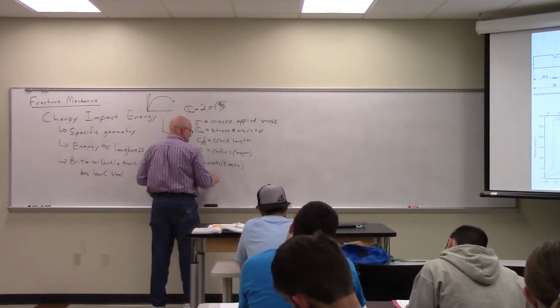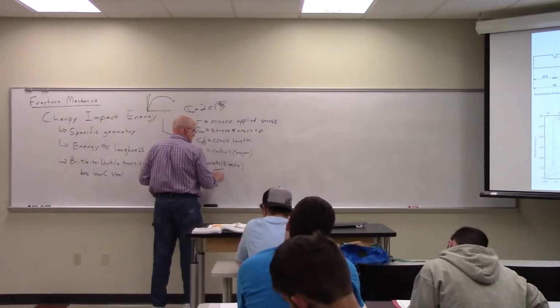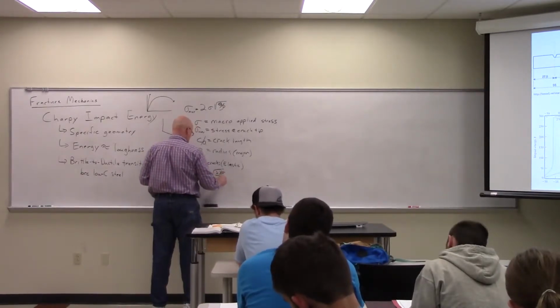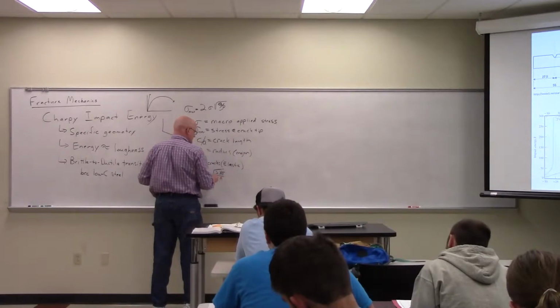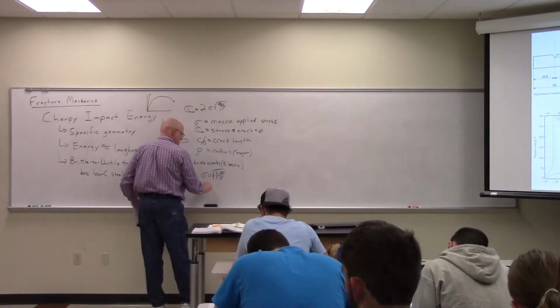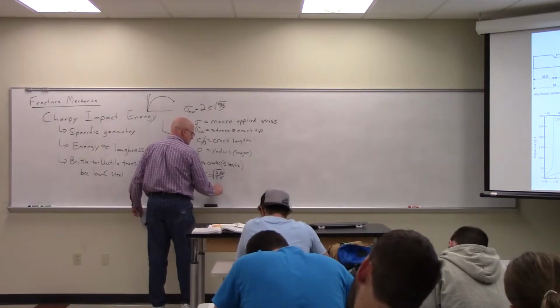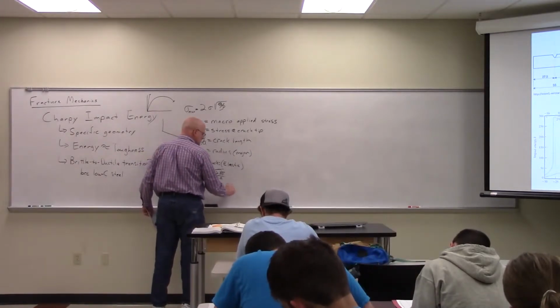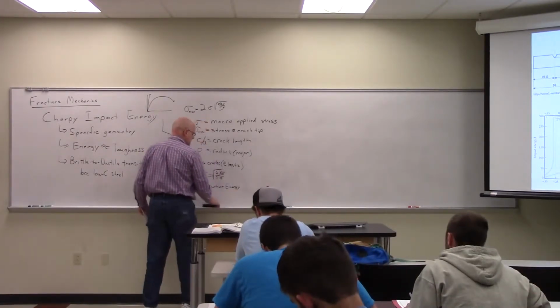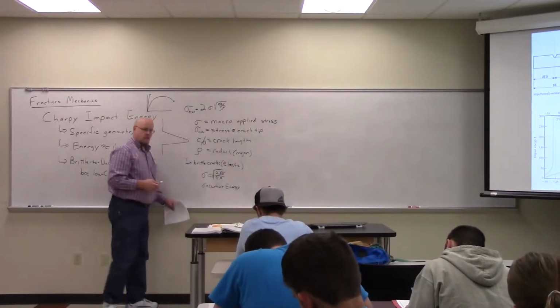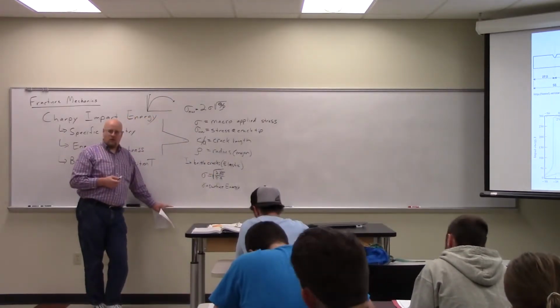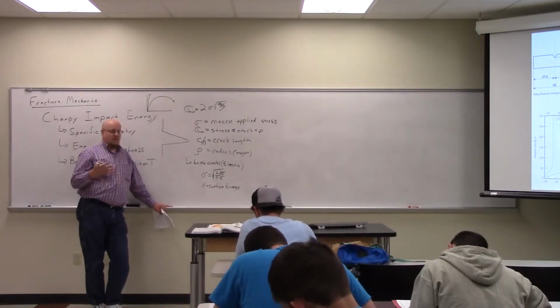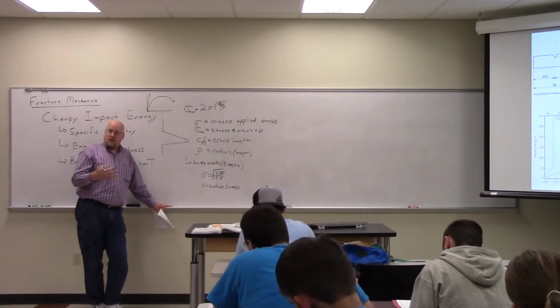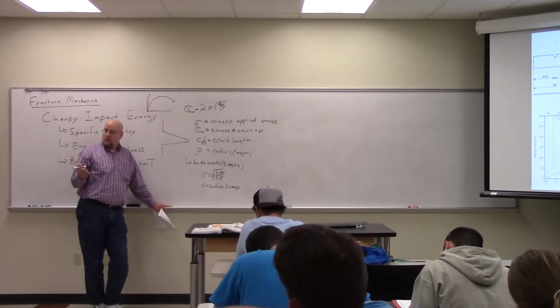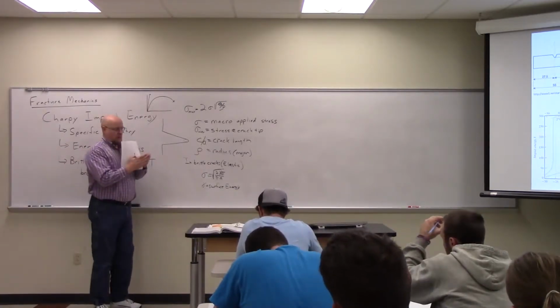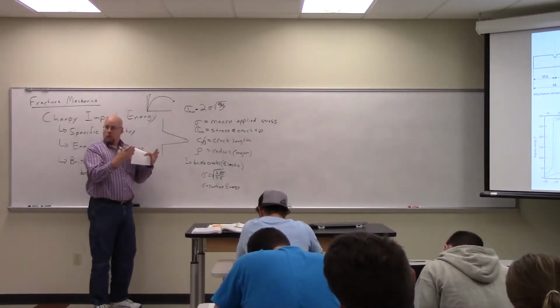So this is the square root of 2 gamma E over pi A. This is not in your book, I don't think. I couldn't find it. Where gamma is the surface energy, E is the elastic modulus, and A is the crack length. So gamma here is the only thing that's new. Basically what we have to do in a brittle material is put in enough stress to create new surfaces. For that crack to grow, I have to break those bonds, create new surface.